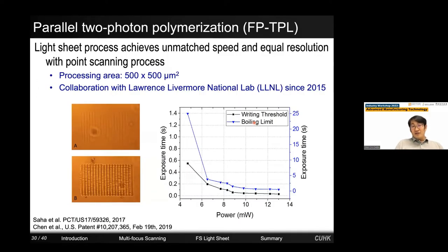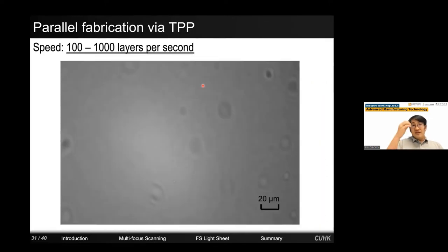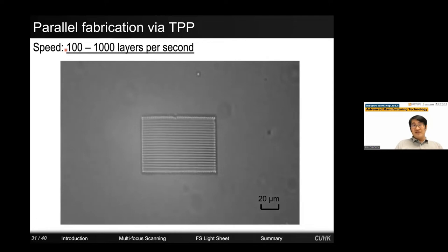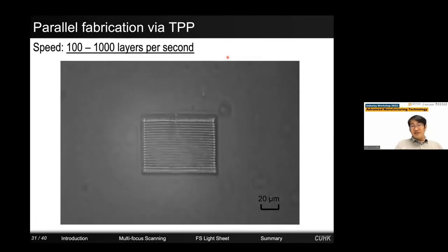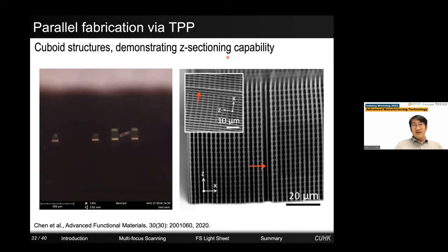We applied this to two-photon polymerization, working with Lawrence Livermore National Laboratory since 2015, where they developed custom-designed photo resins for us to deal with a high power laser regenerative amplifier. You can see, using the system here, each exposure defines a layer, but you're actually seeing a slow motion, because every second we can define roughly 100 to 1,000 layers. This further pushes the fabrication rate of our previous system by one order of magnitude. Once you take out the printed part, it's transparent in an optical microscope, but in an electron microscope you can see fine log pile structures being created. You can also see artifacts or defects caused by a dead DMD pixel.